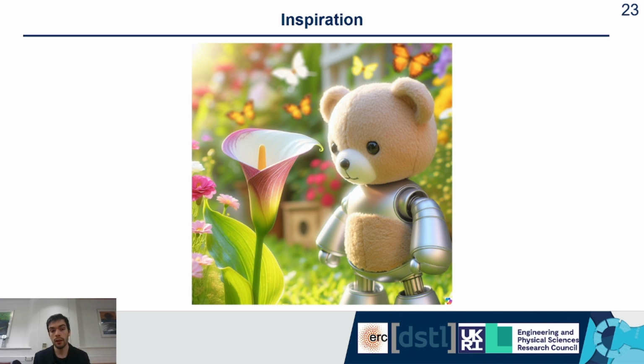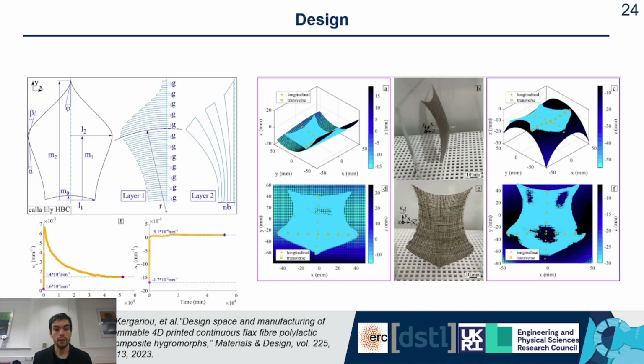So we want to obtain this curl shape from a plain printing structure. That's what we did. This is a printing path on the top left of the screen with two layers. We 3D printed this, then conditioned it from 11 to 98% relative humidity, and obtained this actuation, which is very different from the one of the flower that we've seen before. Basically, we didn't have enough double curvature and we didn't have enough actuation overall.